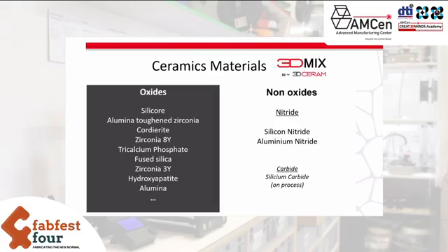About the standard mixes available for our users, we developed some oxides, such as alumina, zirconia, cordierite, alumina toughened zirconia, HAP, hydroxyapatite, and TCP, tricalcium phosphate for biomedical implants, but also some silica-based material for the foundry cores. We also develop nitrides, such as silicon nitride and aluminum nitride, and soon we will offer silicon carbide.